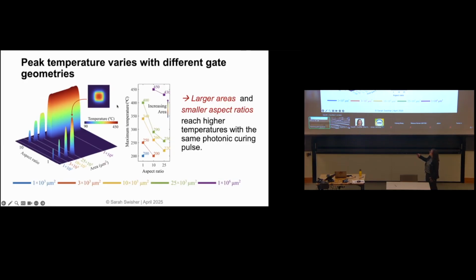So here is a plot showing aspect ratio of 1, so squares versus rectangles, and area increasing going from here to here. And you can see that as a device increases in area, the peak temperature goes up. And as you move from a rectangle to a square of the same area, the temperature goes up. So a square is going to get hotter than a rectangle if it has the same area, okay?